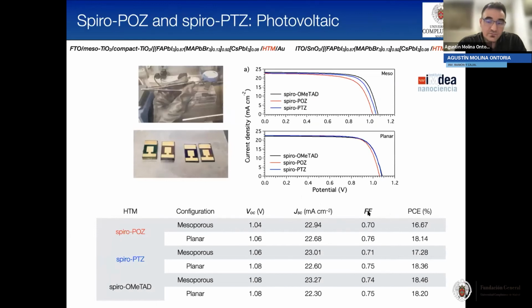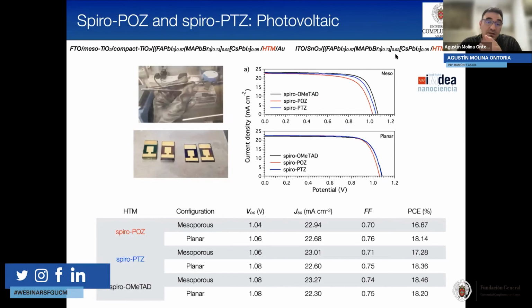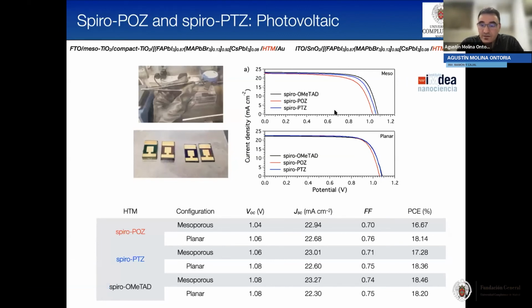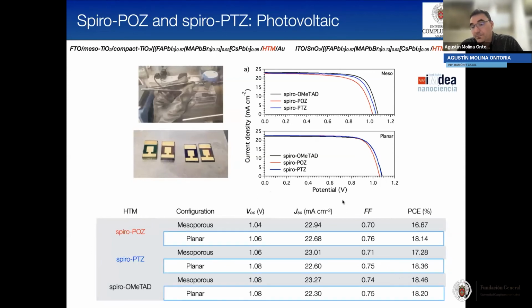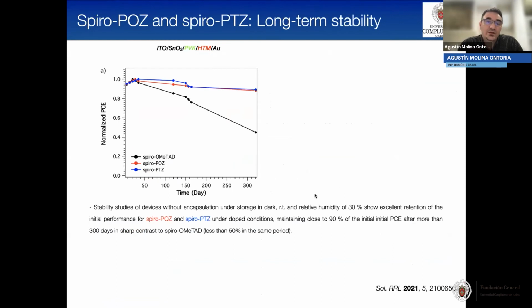We prepared two different kinds of devices: the mesoporous devices that were made in Switzerland, and these planar devices using the triple cation perovskite that were made in our laboratory at Nanoscience. From this table, we can see that in the mesoporous structure, the devices with our hole transporting material perform worse than spiro-OMeTAD. But when we move to planar devices, we get efficiencies pretty much the same or even higher than spiro-OMeTAD. More importantly, what we measured was the long-term stability of these devices. So in this graph, you have the long-term stability of devices in a dark drawer experiment. That is, keeping the devices in a dark drawer and measuring every 10 days or 5 days.